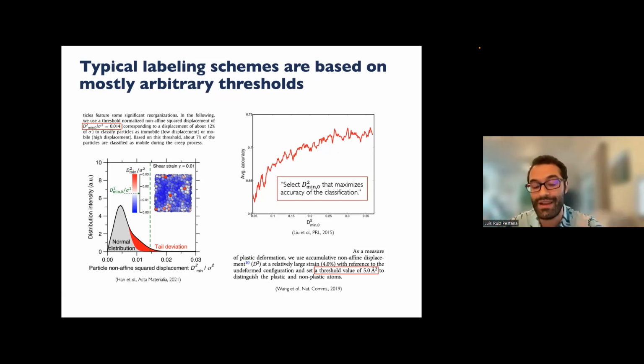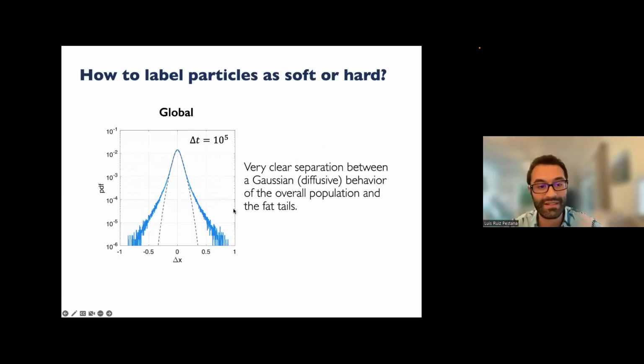So this actually is an arbitrary scheme. It's not very satisfying from a physical perspective, because it feels that there should be something there that tells you what particles are rearranging and which are not. So we found this very unsatisfying, and we developed our own different system to label particles. And it's actually based on the global non-affine displacements.